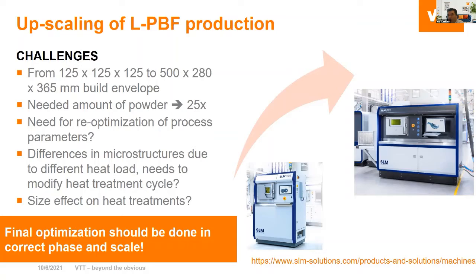that means that in practice the needed amount of powder is increasing really sharply. So we need at least 25 times bigger amount of powder to make a test with the machine. So that is connected to powder availability. But then also process parameter optimization is really important to understand. When the size of the bed is increasing, you probably need some kind of optimization of those parameters. What are the laser parameters in a bigger machine? There is a clear difference between small and bigger machines.